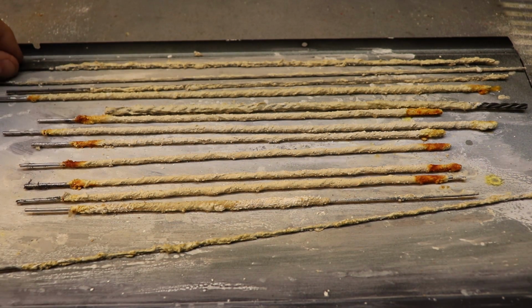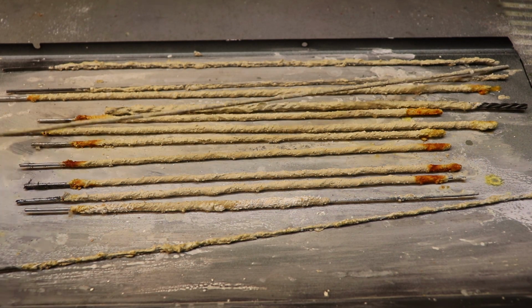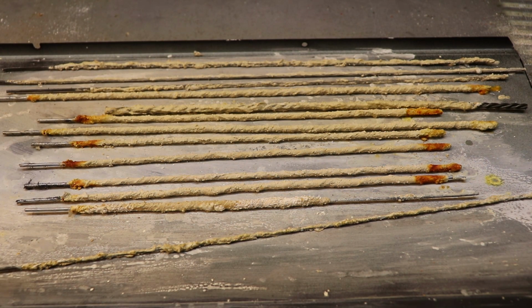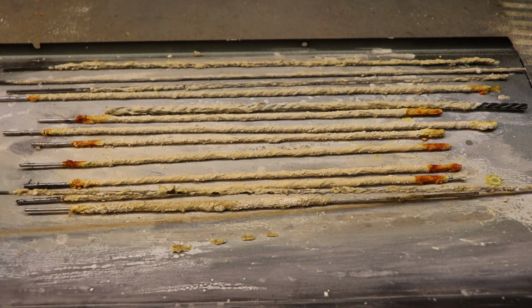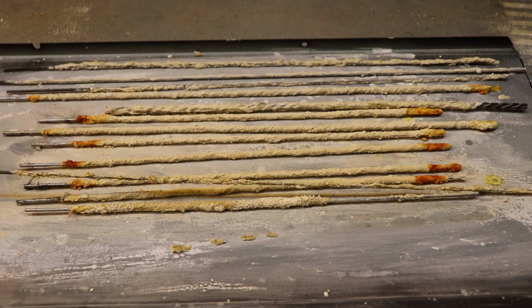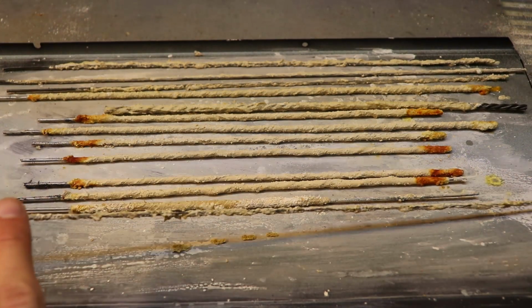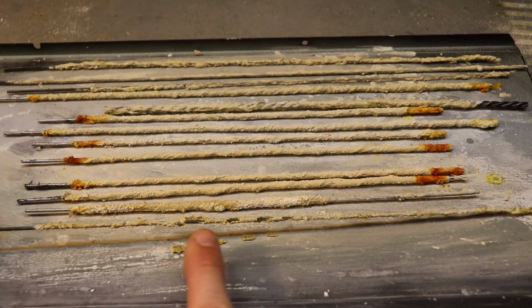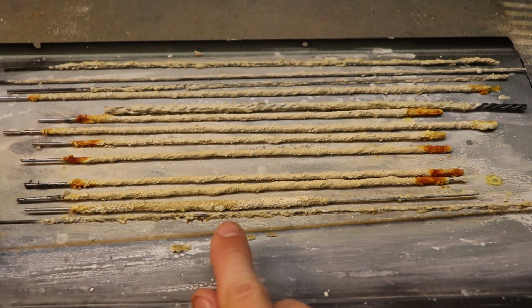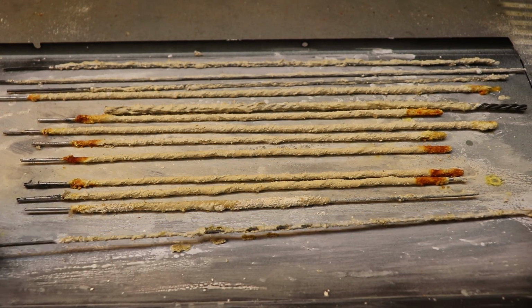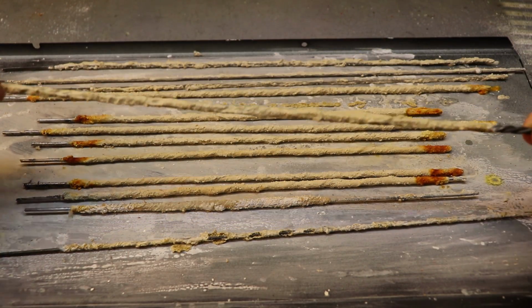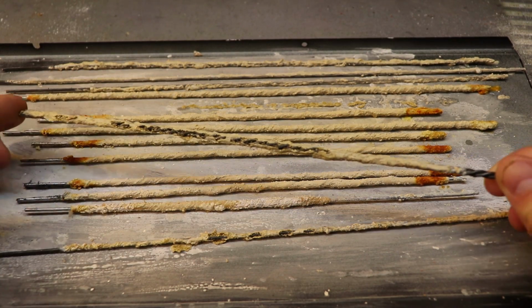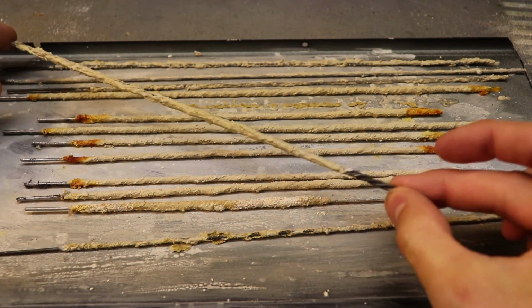And immediately what you can see is that most of these rods look really good. But as you can see, I did try experimenting with coating just a bare wire with the solution because it was sticky enough and thick enough. And so I thought it would stick to just bare metal well on its own, but that wasn't the case. Now, even though the solution did not stick very well on single bare metal wires like this, it did surprisingly well on 3 wires that I put together.